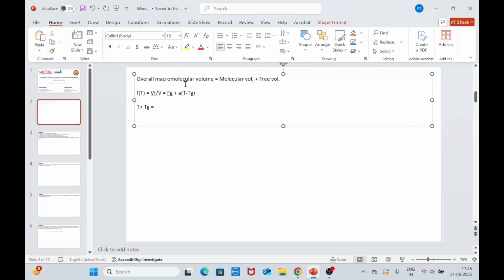Suppose if T is less than Tg, then this will be negative. So Fg minus some value. That means the free volume is going to decrease at a temperature T less than Tg. So at T greater than Tg, Ft increased, and at T less than Tg, Ft decreases. Previously we explained this qualitatively. Here, using this equation, we can see this quantitatively, how the free volume varies with T.